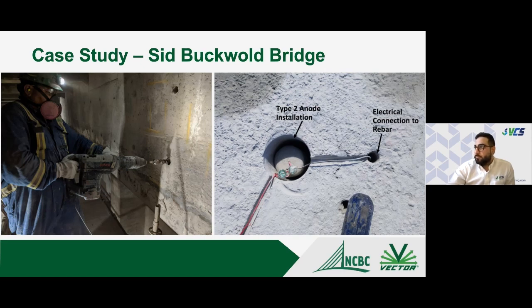Anonymous asks, and I'm going to shorten the question here, have you ever encountered a problem when using both a galvanic system next to an ICCP system installed in the same structure? Again, very, very good question. If you are using an impressed current system, such as titanium or platinum anodes, you would have to be very careful with the location of the ICCP anodes relative to the galvanic anodes, because there will be interference. However, the type 2 anodes,